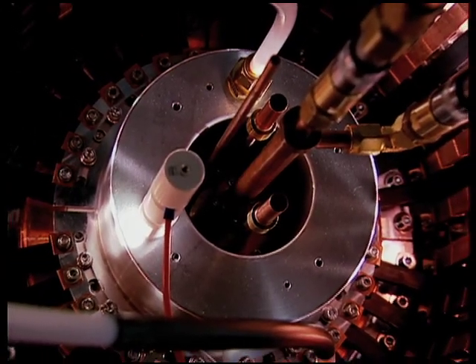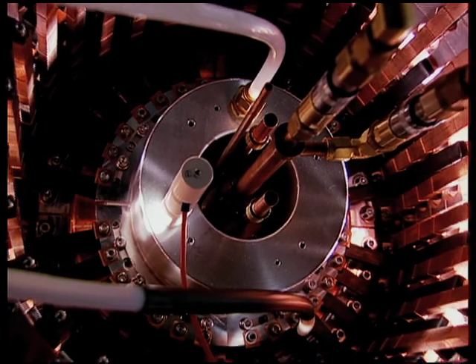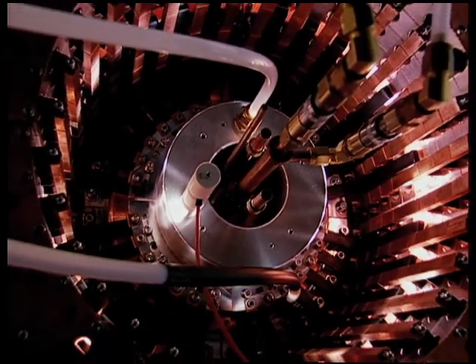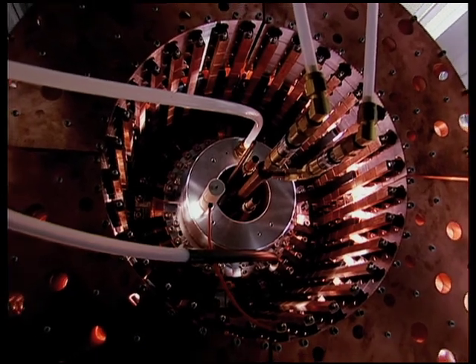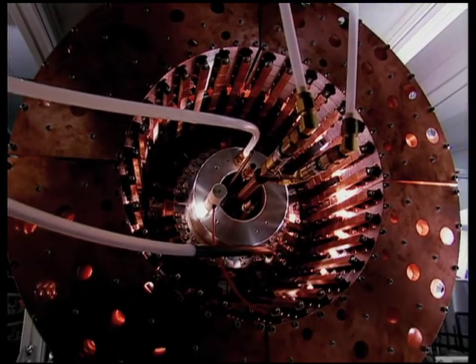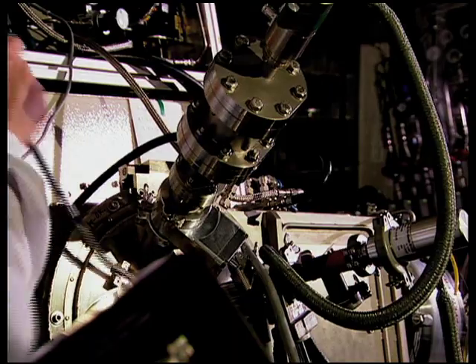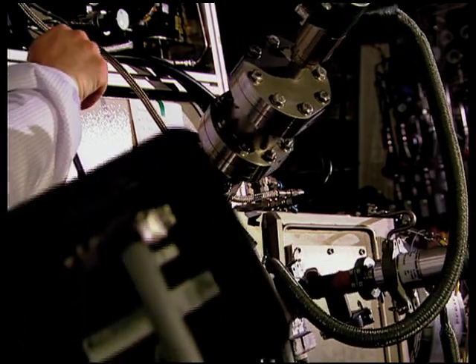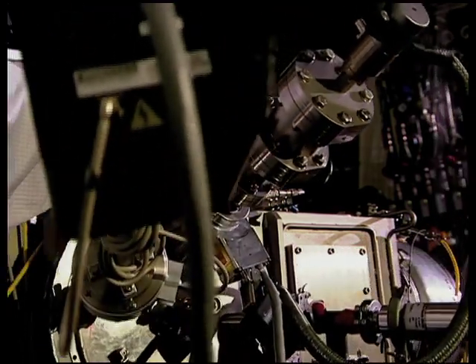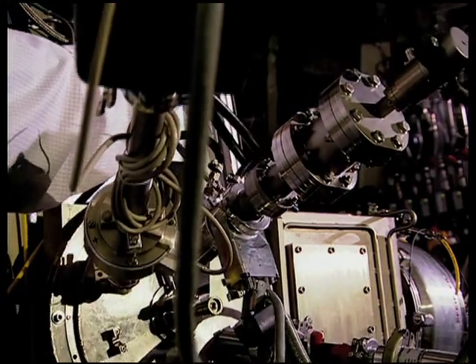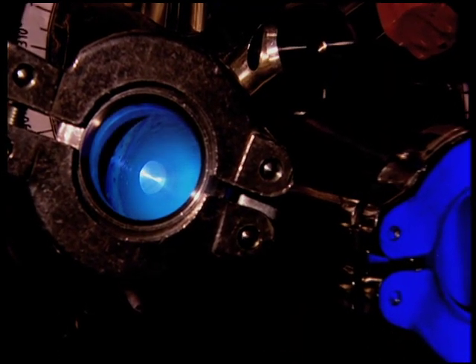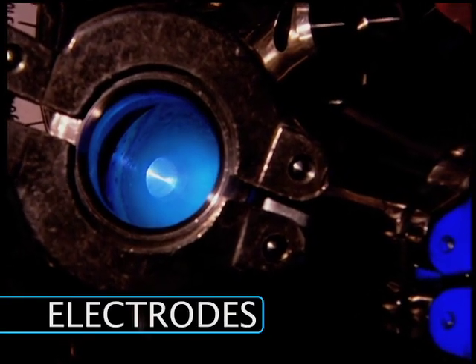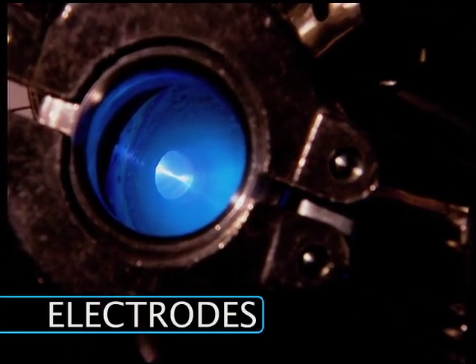One concern is that the source must generate the necessary plasma from the xenon gas, which results in temperatures of several hundred thousands of degrees, concentrated on an area of just a few cubic millimeters. The extremely high energy in the shortwave radiation creates tremendous pressure on all the materials, leading to the very fast destruction of the electrodes. In addition, the whole process has to be conducted in a high vacuum.